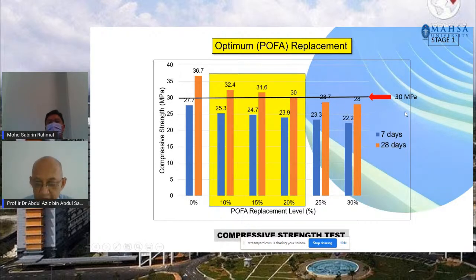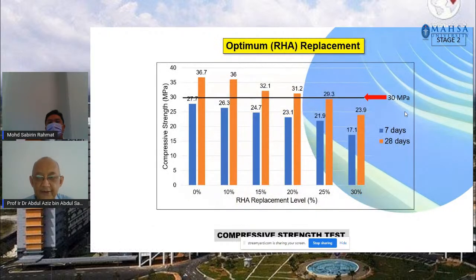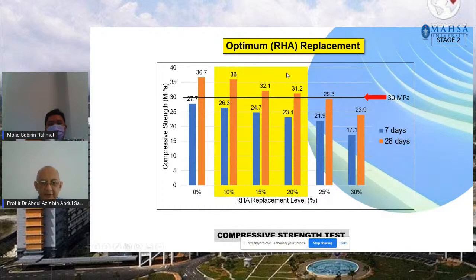Now what about the rice-husk ash? This is the second stage of the work. As you can see there, again the same percentages, from 10% up to 30% of rice-husk ash, were used to replace cement. Again the same trend was observed between 10% to 20% of rice-husk ash as cement replacement. The results of the concrete strength show higher than 30 megapascal. Anything below 30, we will ignore.